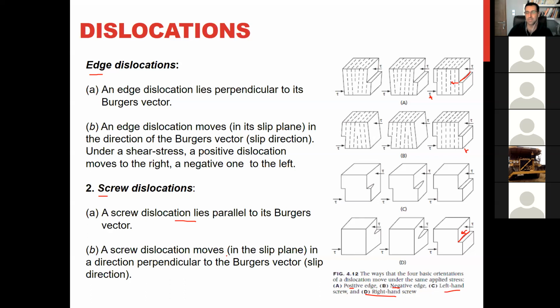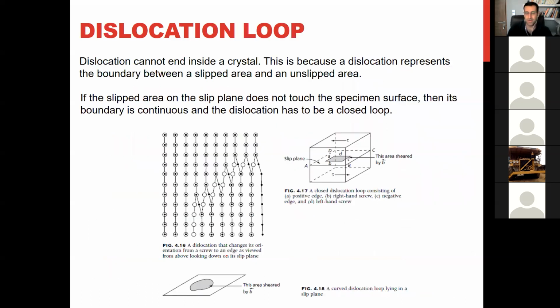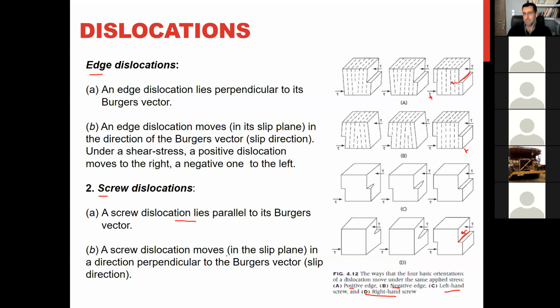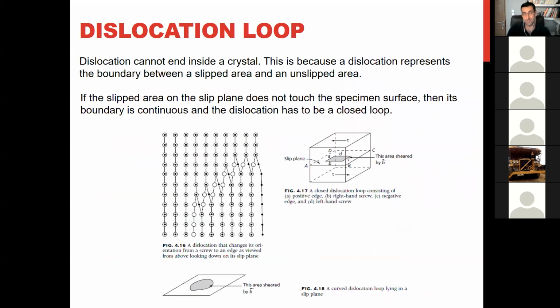So the Burgers vector is something that lets us describe a dislocation with a vector. When you have a dislocation in a metal, it means one part of the metal is slipped or deformed, and the other side of this dislocation is not slipped or deformed. So the dislocation line always divides the crystal into a deformed part and an undeformed part. And we cannot finish a dislocation line inside of the crystal. It means a dislocation must reach the surface. Inside of the metal, dislocations that do not reach the surface must form a loop, like this.